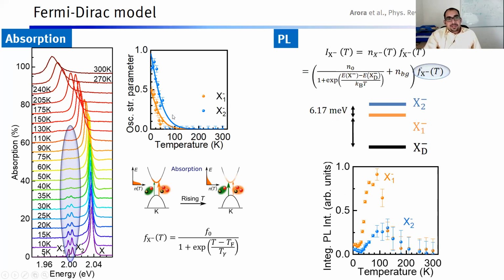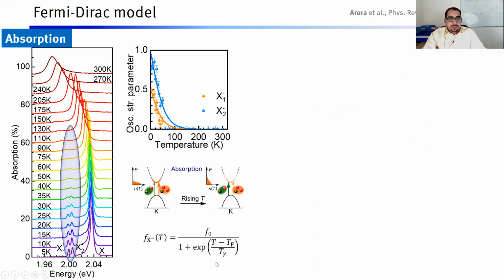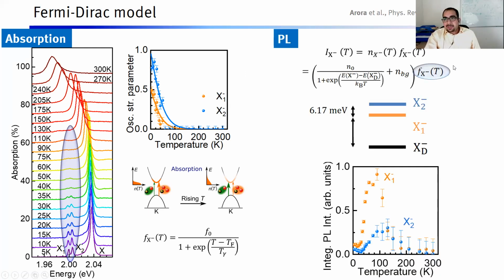So one can fit these oscillator strengths with a phenomenological function, which looks similar to a Fermi-Dirac-like step-like function. One can fit this. And once we fit this, we introduce this function here, and then there is only one free parameter left because this function is coming from the experiment itself. So this parameter left is now just the energy separation between the bright and the dark exciton, trion, bright and dark trion.